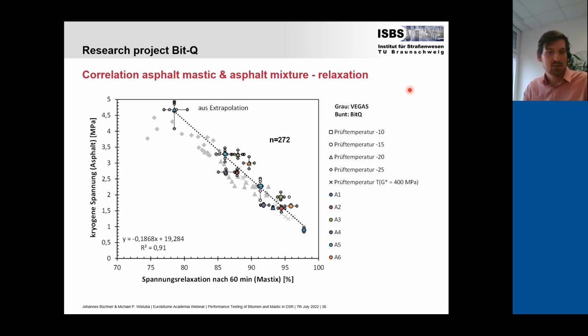Now we did exactly the same as before. We slightly varied the test temperatures, but the overall test methodology is the same. So I can just present the same results as before in the correlation analysis. In the background, you can see the gray points, which were the results from the previous research project. And now in color, you can see overlaid the new results from the 6 plant-produced mixtures, where we produced the mastic correspondingly in our lab and carried out the performance tests accordingly.